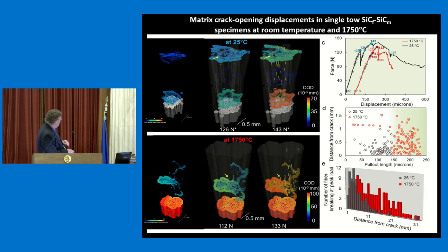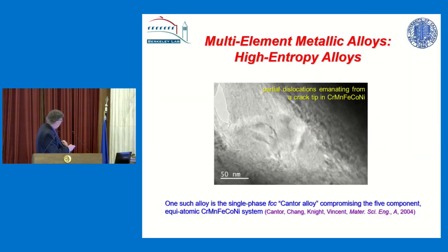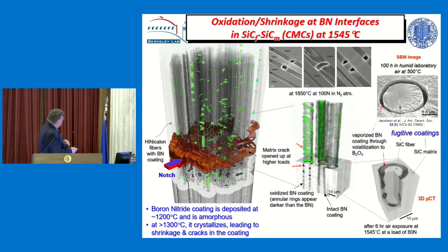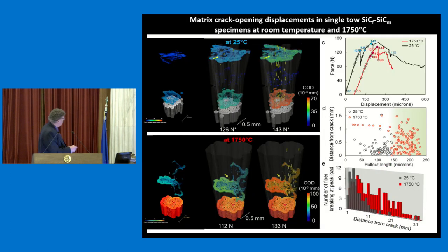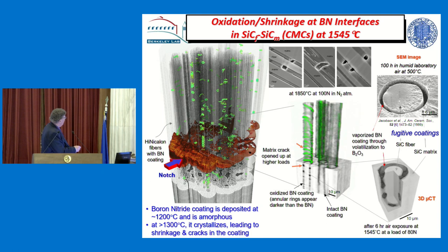We can even look at actually oxidation. Another one of these materials happens to make the fibers move so they can pull out a little bit to give you more resistance. They coat them with boron nitride. The trouble is the boron nitride starts to move, the boron moves, and it can cause cracks.